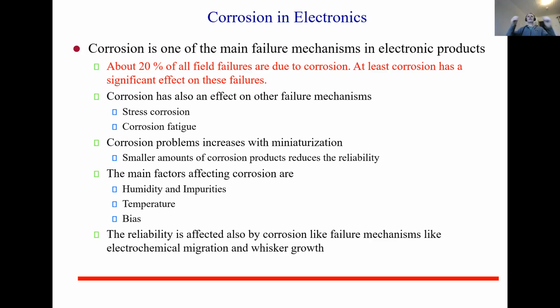So that is the point, that you have again these cumulative effects, which when we are talking about corrosion might be completely something else than these damage accumulation models where you sum up 50% damage and 50% damage, then it's 100% damage and fracture. So you remember that in Jonas's slides there was this damage accumulation, and then I showed it from Juha's doctoral thesis, these approaches for how one should consider the microstructural effects in order to really understand these kinds of combined loading conditions where 1 + 1 is not 2. 1 + 1 might be even 10 in some cases, like stress corrosion or corrosion fatigue. Okay.